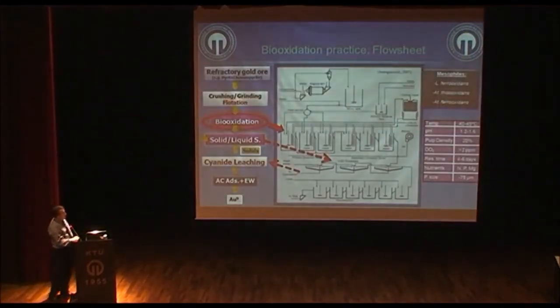So when we look at bio-oxidation practice, it is a suitable method for refractory gold ores, which are treated by physical pretreatment methods like crushing and grinding, and then floated to obtain a flotation concentrate. Here, this flotation involves the flotation of pyrite and arsenopyrite as the gold-bearing phases.